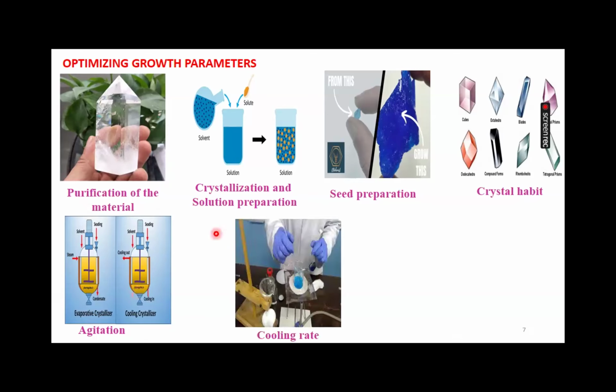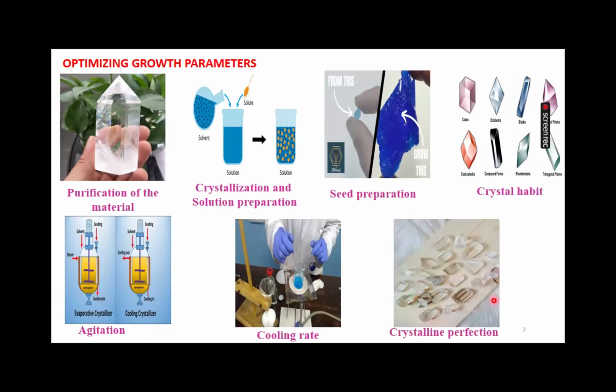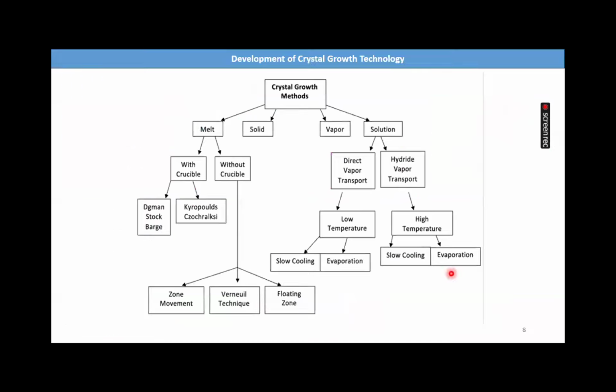Cooling rate. In the growth solution, the temperature is decreased in order to achieve the necessary supersaturation, which is what propels crystal formation. The programming should be done to match the cooling rate to the crystal growing rate. Crystalline perfection depends on factors such as purity of the starting material, cooling rate employed, quality of the seed crystals, and the efficiency of agitation.